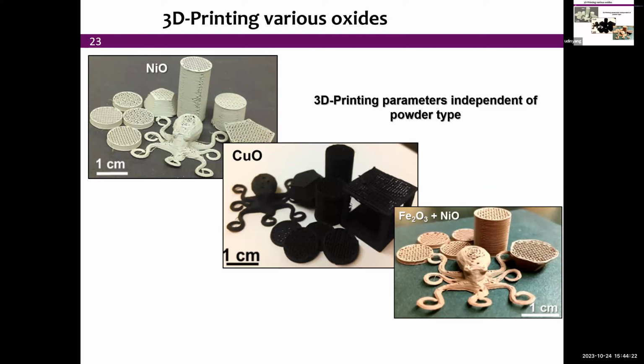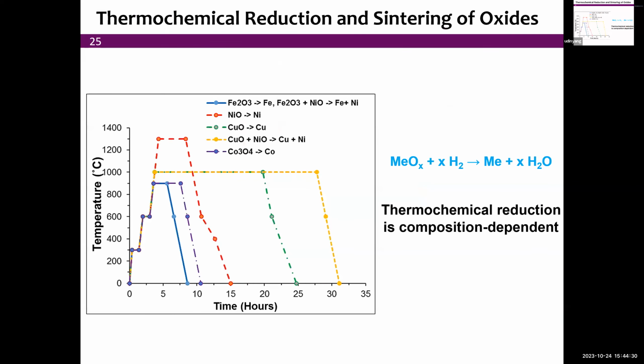Cannot do it with titanium, but we can do it with iron, nickel, cobalt, copper, tungsten, and even molybdenum, as I will show in a minute. So the inks can be printed pretty much always under the same conditions. It's only a question of how big the particles are, but the sintering and reduction now depends on the temperature at which the reduction takes place.